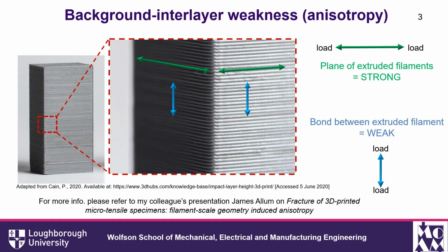However, this layer-wise strategy normally results in the main limitation of MEAM parts, and that's anisotropy, or more specifically, the weakness between extruded filaments as shown by the blue arrows. In contrast, when the filaments are laid down in the direction of tensile testing load, as shown by the green arrow, they're known to be stronger. Therefore, in this study, we decided to consider the weakest part as well by building our tensile testing specimen in the vertical direction. More information about anisotropy and interlayer weakness will be given by my colleague James Allum, so please refer to his